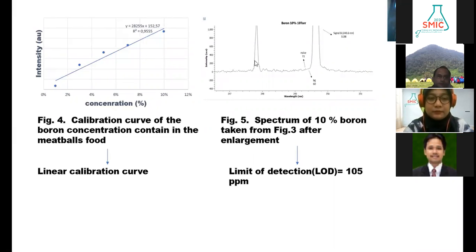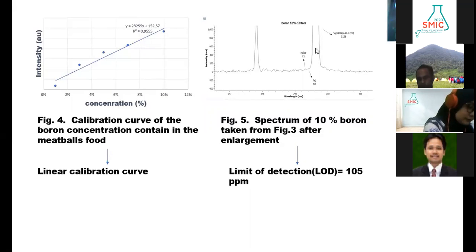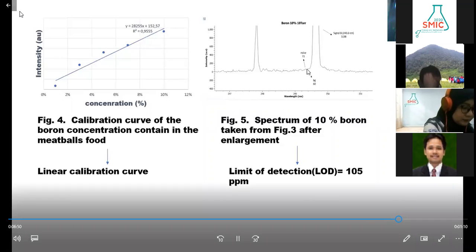Also, by using the spectrum of 10% boron concentration, we calculate the limit of detection of boron by using the criterion that the minimum intensity of the line emission is three times higher than the noise. By using this criterion, we calculated that the limit of detection in this experiment is 105 ppm for boron emission.